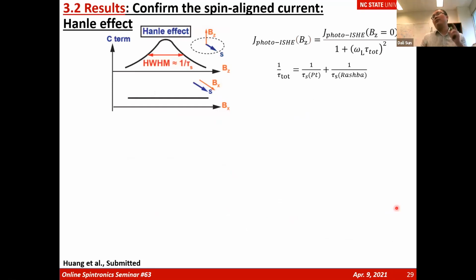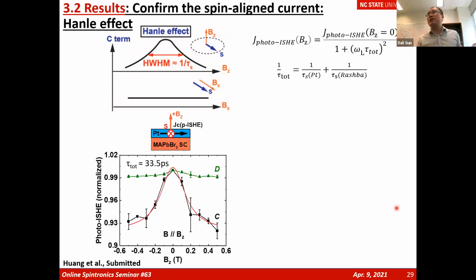That's what we did. When demonstrating the spin current injection into platinum by applying a vertical magnetic field, the spin information will start to precess. Then your photocurrent responses should decay as a function of magnetic field with a Lorentzian shape. By measuring the half-width at half maximum, you can get a spin relaxation time, which is considered for platinum and Rashba state together. If you apply a magnetic field parallel to the spin polarization, then no Hanle responses should be expected. Well, we measure the same responses in the same structure by applying a magnetic field.